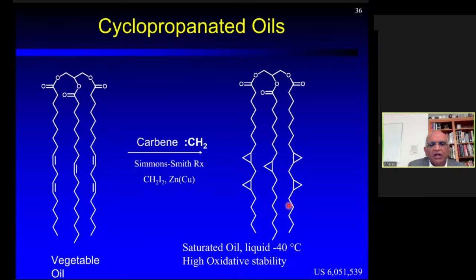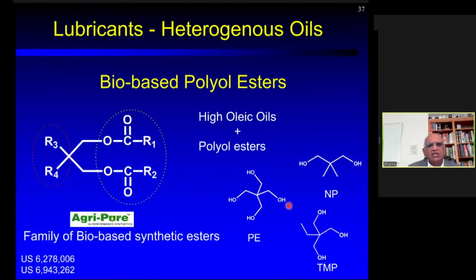So we wanted to apply a different kind of approach to create a material that can be commercialized. So we looked at creating heterogeneity within the molecule, within the composition. The way we have done it is we wanted to create the heterogeneity both at the acyl chains as well as the backbone by reacting with different polyol esters. The way it is done is the high oleic oils are transesterified with the polyol esters. Various polyols that we have utilized are shown here: neopentyl glycol, trimethylolpropane, and pentaerythritol, which contain diesters, triesters, and tetraesters. These molecules, when they are esterified, give a family of bio-based synthetic esters that were useful, which I will show in the next slide, the chemistry of it.